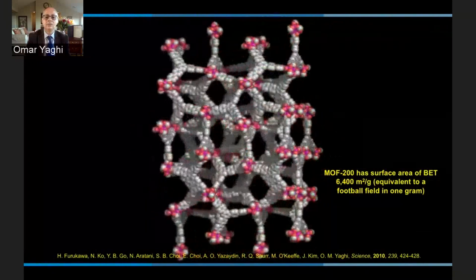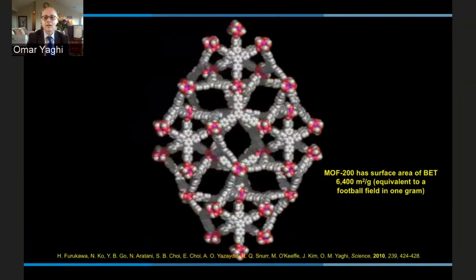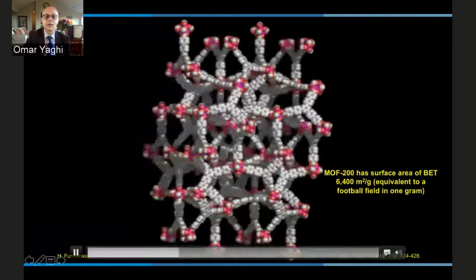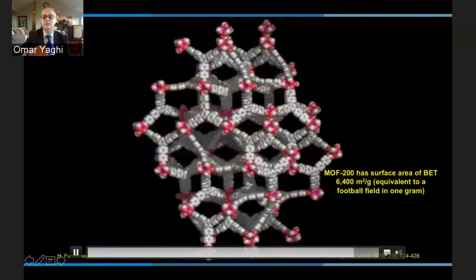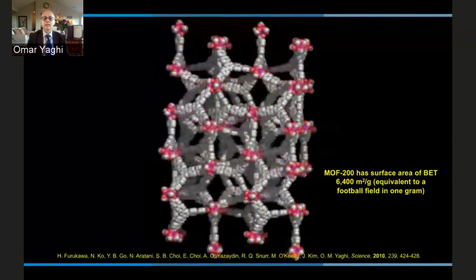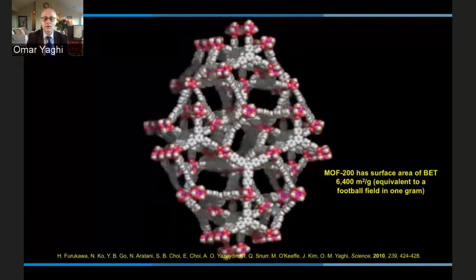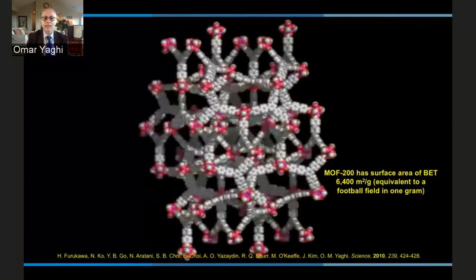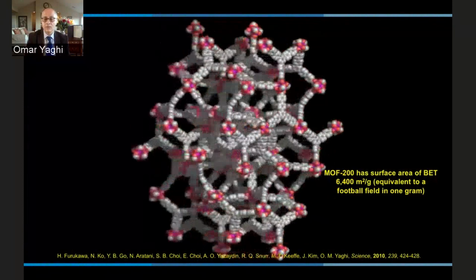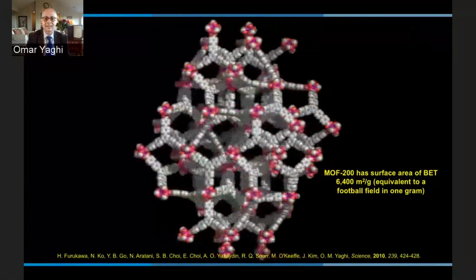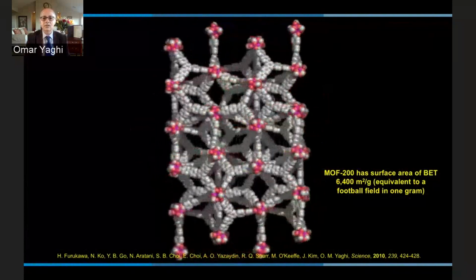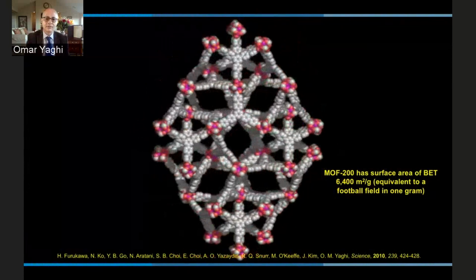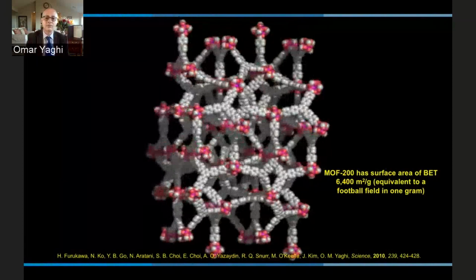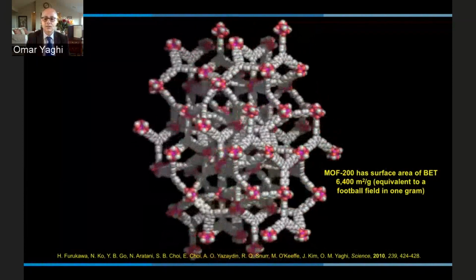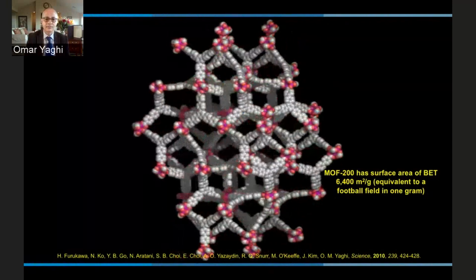And so we needed to even go beyond the surface area of MOF5. And so we designed this structure from trigonal organic units with the same SBU as MOF5. And you see that the surface area is 6,400 square meters per gram. And so the very first thing to know about MOFs is that all the atoms are surface atoms. And they have pores, but the pores do not have walls like other porous materials. So they can be thought of as entirely scaffolding, and that's why they have extremely high surface area. But also the fact that the pores have no walls allows substrates to move in and out of the pores with great facility. And that's another great advantage of MOFs.